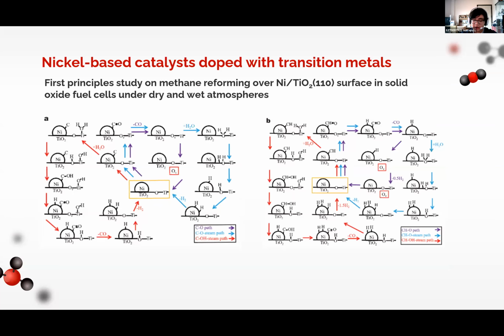The latter reacts with the deposited carbon to form carbon monoxide, reflecting the positive impact of lattice oxygen on the elimination of deposited carbon. In addition, in the humid reaction environment, the generated steam can occupy the oxygen vacancy and adsorb on the surface of titanium oxide, facilitating the removal of carbon deposit. Moreover, the adsorption of water can effectively lower the reaction energy and facilitate the occurrence of the reaction.